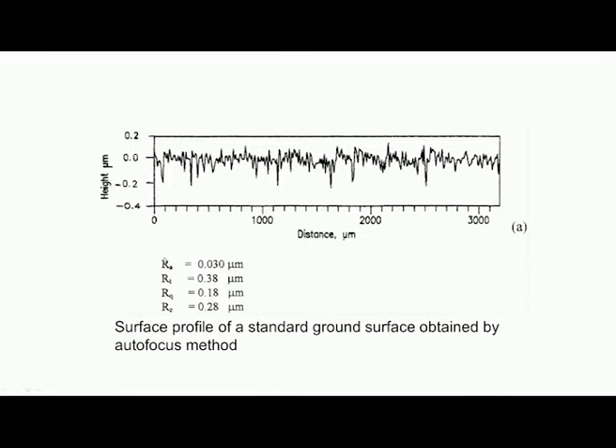Now, this is one result obtained by the optical profilometer. This is the surface profile of a standard ground surface obtained by the autofocus method. Okay. Now, the x axis is distance in terms of 1000 micrometer, 2000 micrometer like that. So, a small division indicates 100 micrometer, and these are the peaks and valleys on the surface. After processing the data, the Ra value was calculated to be 0.03 micrometer, Rt value is 0.38 micrometer, and Rz value is 0.28 micrometer. Now, the same surface was checked with a stylus instrument, and then the comparison was made.